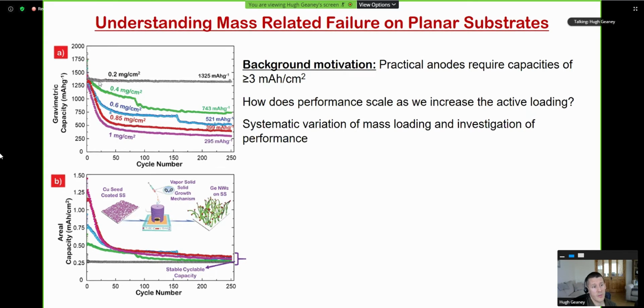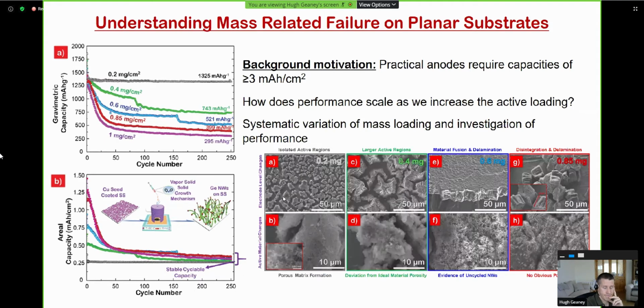Whereas with the very light samples the performance was absolutely rock solid, as we increased the loading it started to decrease. In terms of the areal capacity, this is the same data just plotted as areal capacity, and you'll see that they all started to bunch together towards the bottom. So with this setup, we couldn't achieve a capacity over 0.5 milliamp hours per centimeter squared after 250 cycles.